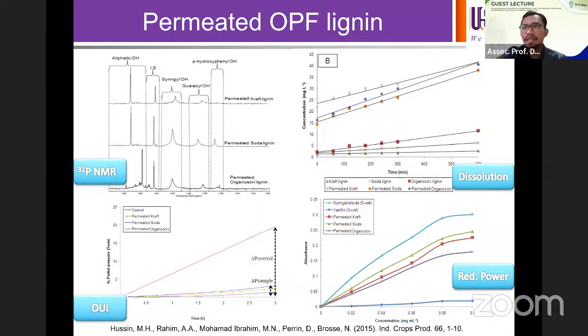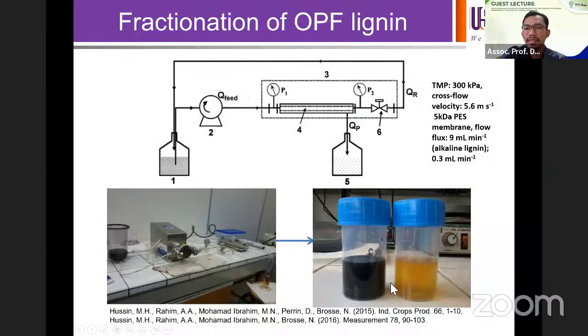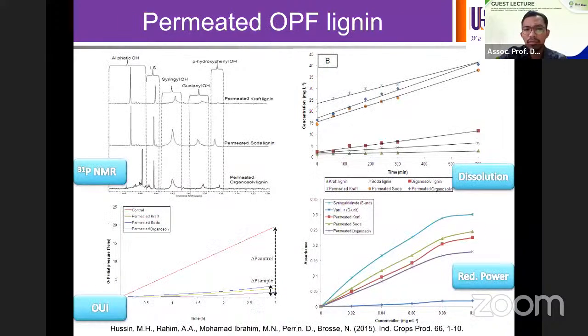And after we obtain the permeated black liquor, we precipitate it, we obtain the lignin, and we characterize it again, of course, using phosphorus NMR. We check on the antioxidant activity and also the dissolution. So from here, you can see that the fractionated lignin produces better properties in terms of antioxidant as well as the solubility.